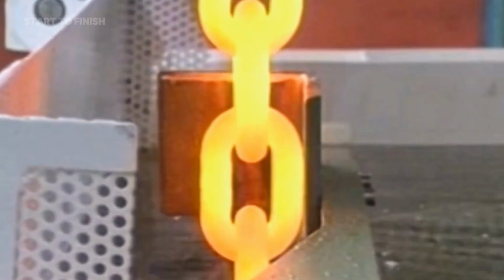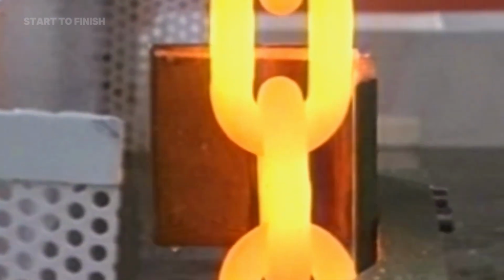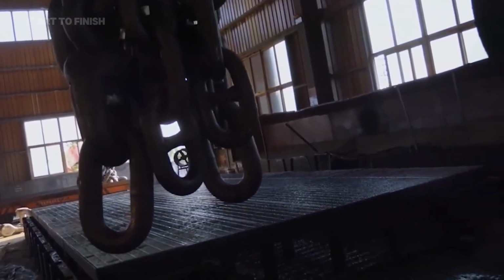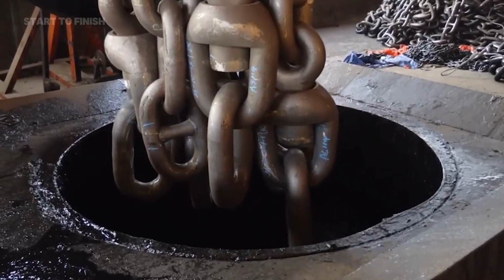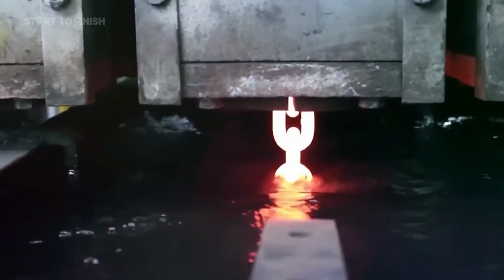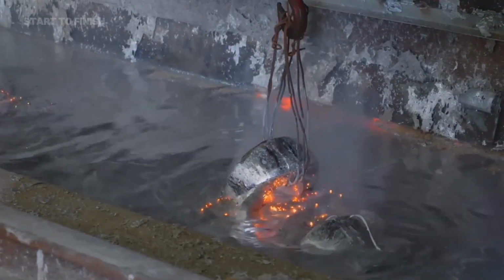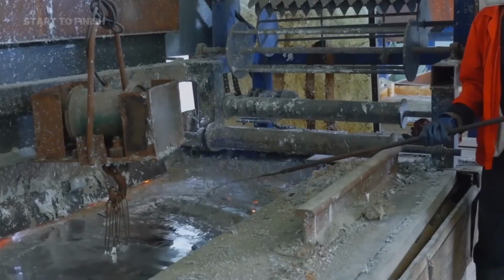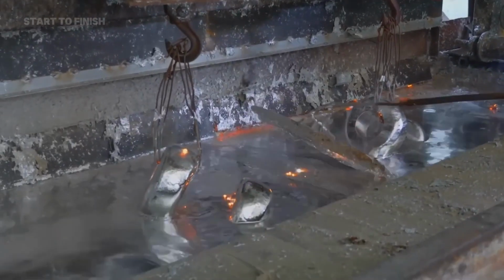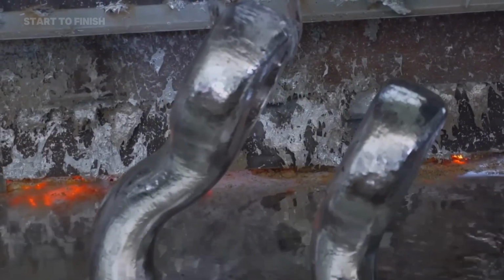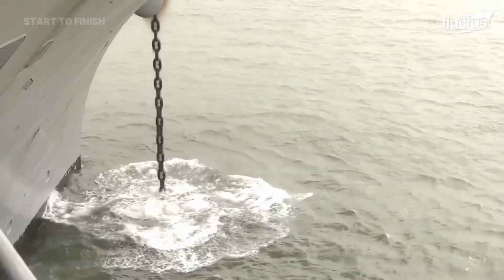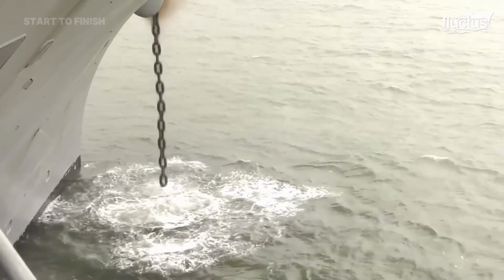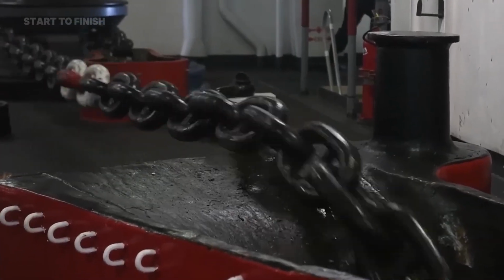Once the surface is cleaned, each chain length is chemically washed in an alkaline solution to neutralize impurities. Automated cranes then lower the chain into galvanizing or coating tanks, depending on the customer's specification. For most marine applications, the preferred method is hot-dip galvanizing, submerging the steel into molten zinc heated to over 450 degrees Celsius. The zinc bonds metallurgically to the steel, creating a corrosion-resistant alloy layer. When exposed to seawater, the zinc slowly sacrifices itself, preventing the underlying metal from rusting.